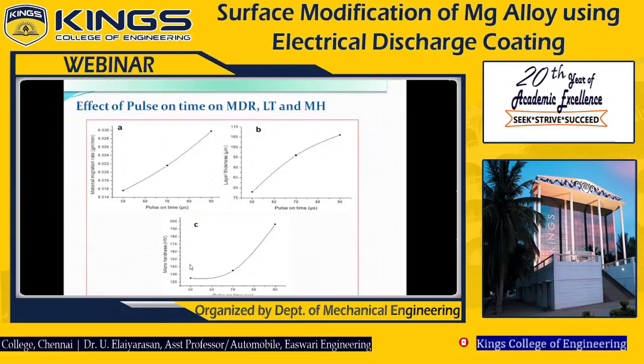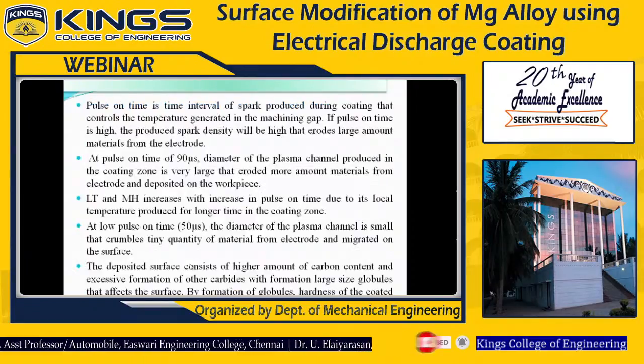Here at low pulse on time, low migration rate, low thickness and low micro hardness. Further increasing the pulse on time, more quantity of material crumbles from the electrode and is deposited over the surface. So if a higher migration rate is achieved, the layer thickness can be improved and micro hardness is also improved. The pulse on time means the time interval of spark produced during the coating that controls the temperature generated in the machining gap.